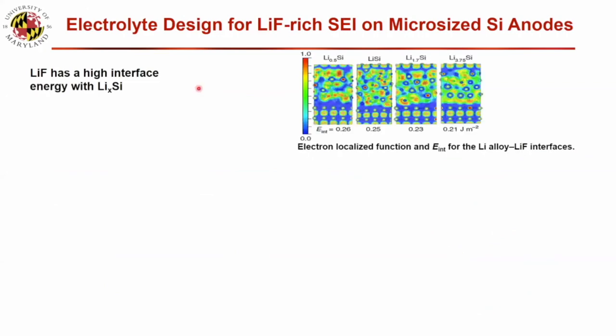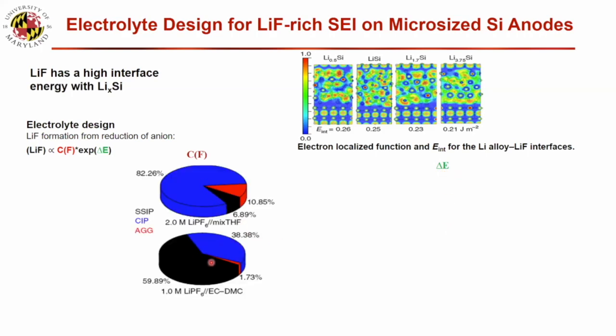And then we demonstrate this, first for silicon. We calculate lithiated silicon at different levels. We calculate the interface energy with lithium fluoride, and it has a high interface energy. Second, we try to form a high concentration of lithium fluoride in the SEI. That depends on the concentration of the anion, and also the potential difference between the anion reduction potential and the solvent. So this is where we demonstrate traditional electrolytes.